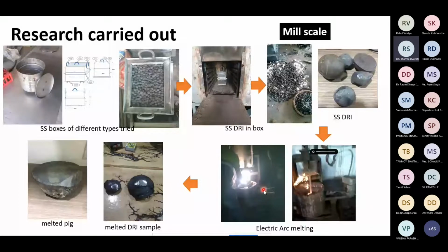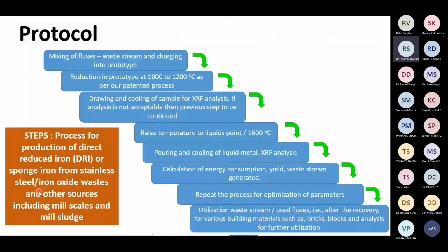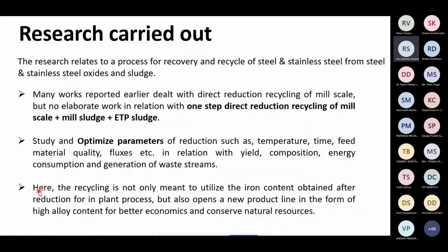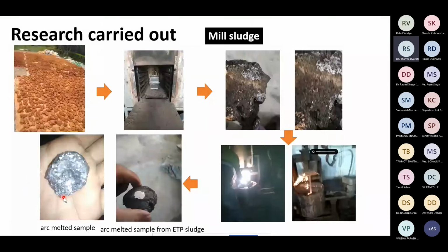So this is simply iron as good as that taken out from the blast furnace, the same. So it is 100% recycled. That study was also carried out by us with the help of various industries, and we observed that this mill scale can be easily recycled. This process gives one sort of assurance that waste generation from the steel industry can be further reduced. This kind of research is not reported even in the literature, that this sludge can be recycled back into the steel industry itself using this process.